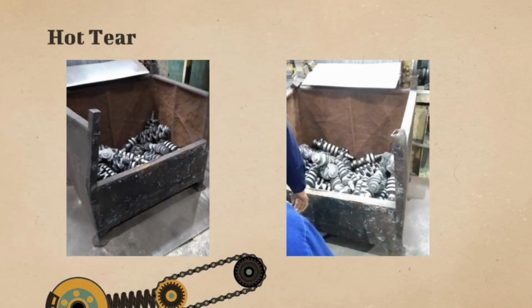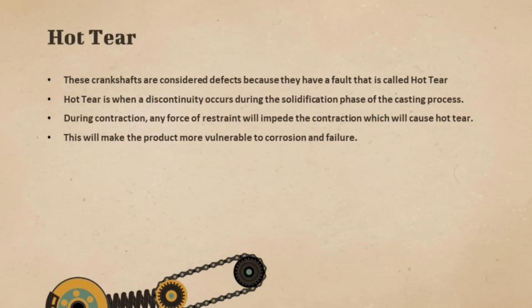Next, we move on to the defect of hot tear. These crankshafts in the picture are considered defective because they have a fault called hot tear. Hot tear is when a discontinuity occurs during the solidification phase of the casting process. During contraction, any force of restraint will impede the contraction process, which will cause the issue of hot tear. If a product has a hot tear defect, it will be more vulnerable to corrosion and failure. And that is all for the defects.